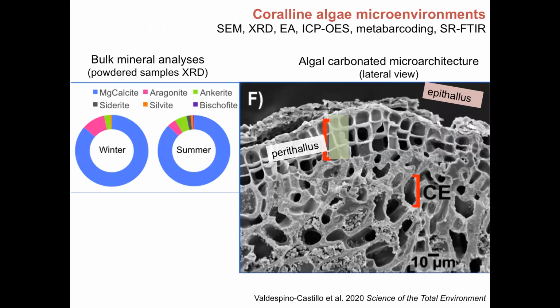In this slide, I am showing some relevant findings regarding the microstructure. And to the left, you can see the mineral composition based on bulk mineral analysis of powder samples by X-ray diffraction. The main component is magnesium calcite, as has been reported broadly in the literature. But we also found aragonite and 2 iron-containing carbonates, siderite and ankerite. This last is a dolomitic carbonate. Interestingly, we found sylvite and bischofite in the summer samples, and these are evaporitic minerals known as potash salts.